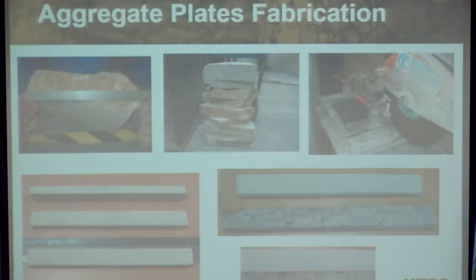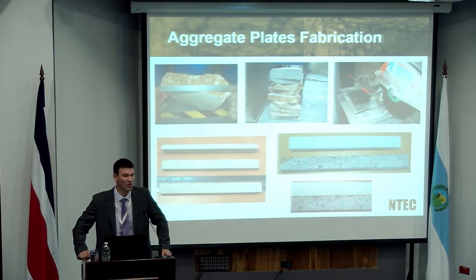The very first thing to do is to obtain your aggregate substrates. And straight away, this is an issue because our stones that we use in our asphalt mixtures are not the correct size to allow us to produce a geometry for a peel test. A peel test will require you to have a substrate of at least 200 millimeters in one dimension. So effectively, our aggregates that we would use, even if we're using very coarse aggregates, are going to be nominally 40 millimeters at the most.